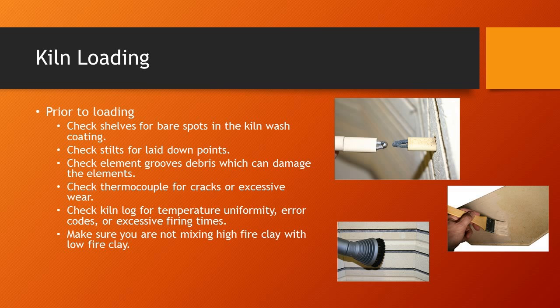Okay, so before you load the kiln, check your shelves to make sure that there's no bare spots. By bare spots, I mean areas where the kiln wash has come off of the shelf. Because if you have any glaze run off a piece onto that bare spot, then that pot will become fused to the shelf, and you'll have to break it off and then grind the shelf. So always inspect your kiln wash.